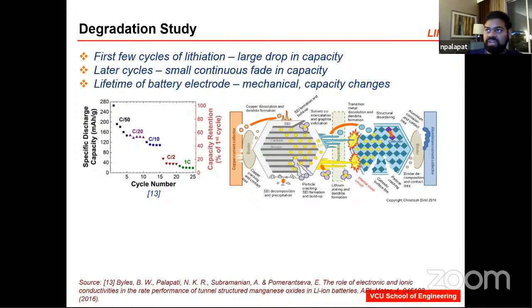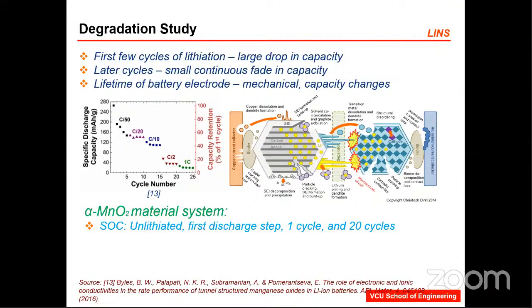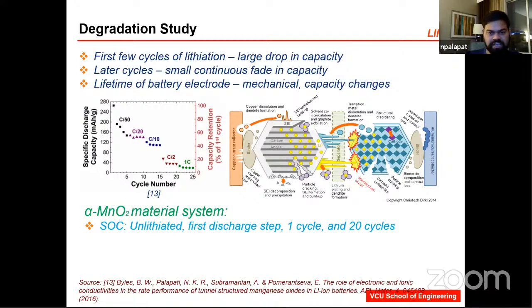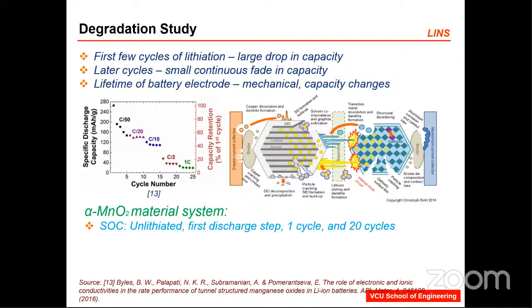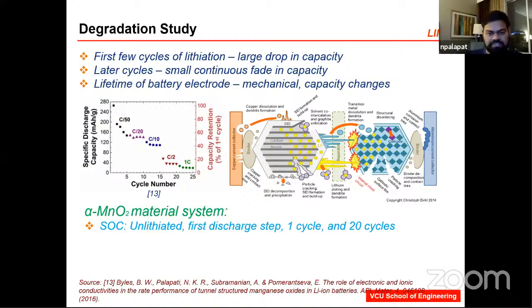So in my material system, I have extended it from one cycle to 20 cycles. And I wanted to see how the material performs at each of the charging cycles, how it behaves at charging, how it behaves at discharging, and I repeat the number of cycles at each point. So I chose 4 volts as my charging voltage and 1.5 volts for discharging.